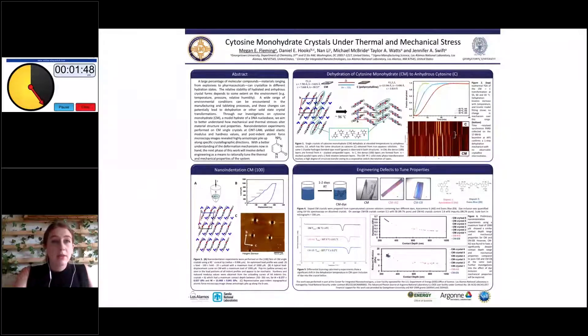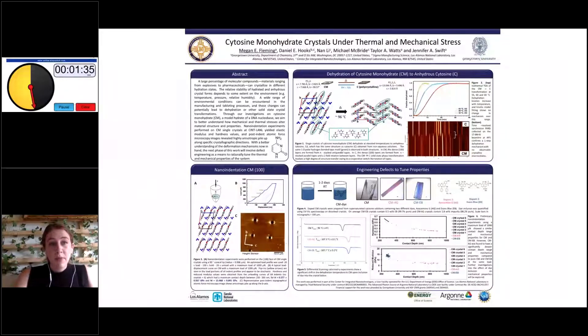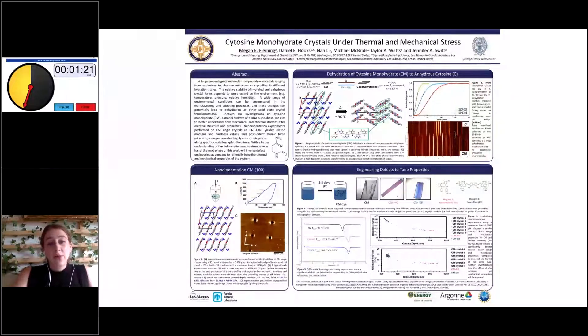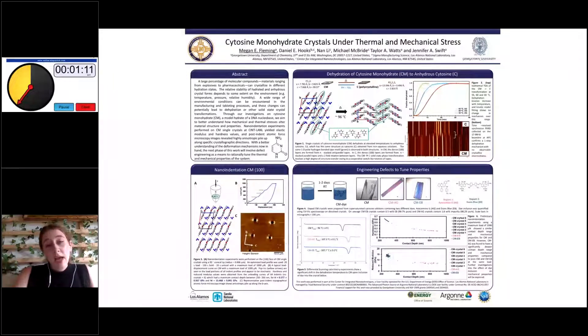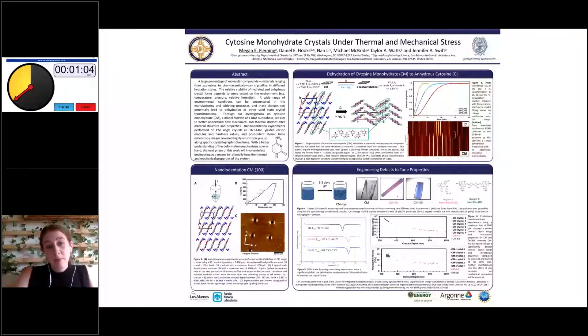After understanding the thermal mechanism, we wanted to look into the mechanical processes as well. In the bottom left, you can see our nanoindentation experiments — the tip indenter relative to the (100) face, which is the major face of the crystal. A load-unload profile is shown in the top right of that box, where we noticed some pop-ins, which are commonly seen. We were able to extract both hardness and modulus: hardness was approximately 0.577 GPa and modulus approximately 13.47 GPa. In the atomic force microscopy image, we also observed anisotropic pile-up after post-indent imaging that follows the crystallographic axes.